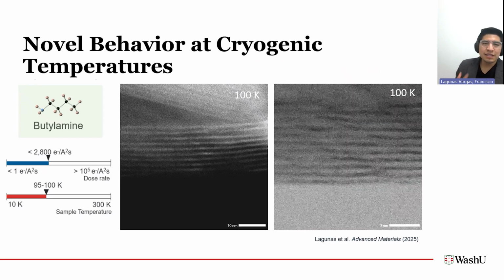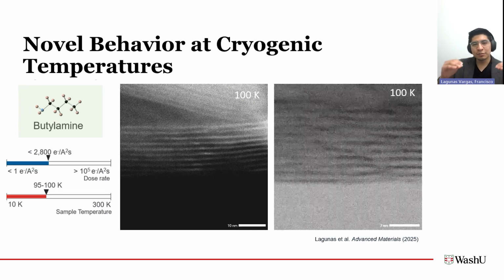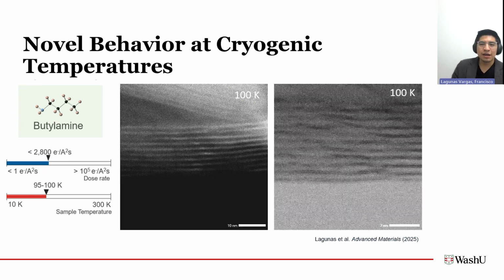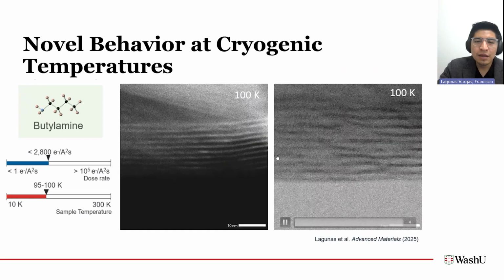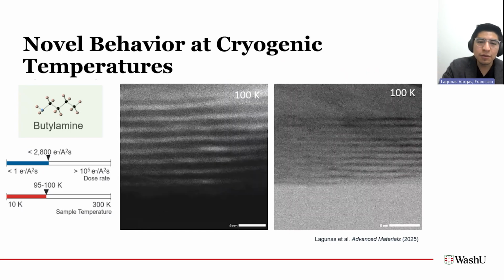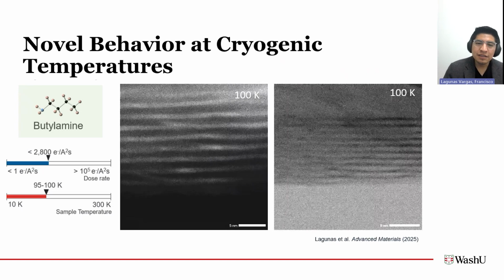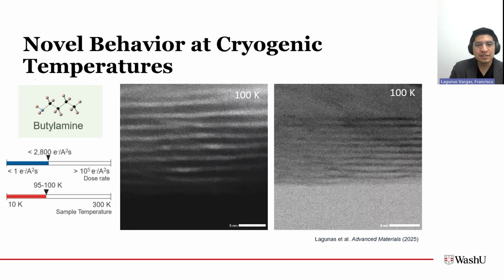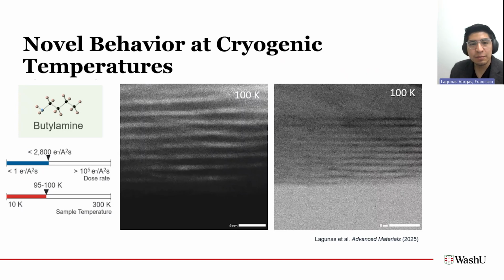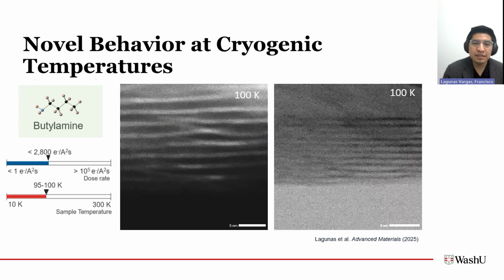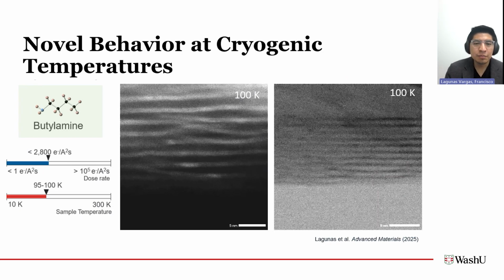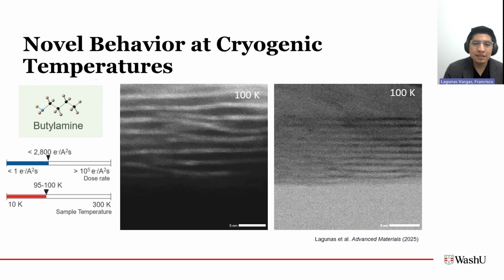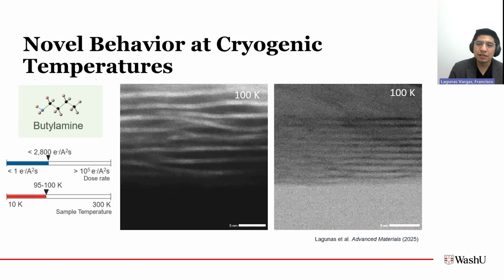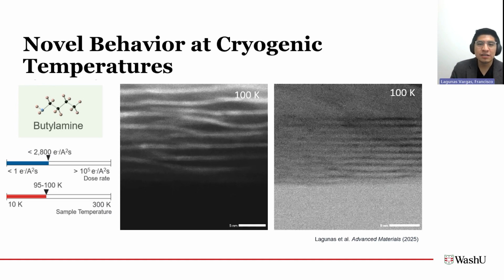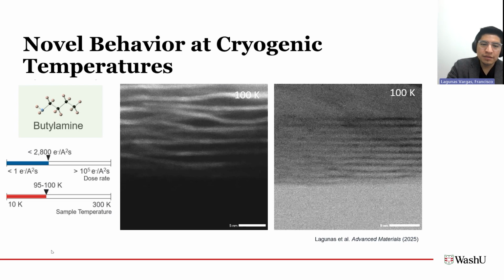So what happens when we look at these same materials when they're starting in their pristine condition, and then we start breaking them down with the electron beam? Well, pause this one on the left. If you could focus on the middle one, this is us looking at a MXene that started near its basal plane spacing that we measured in XRD. So we expect it to be in its pristine state. And then as we start applying more and more electron dose, you can see the material degrades in a really significant fashion. So I'll pause it right here.